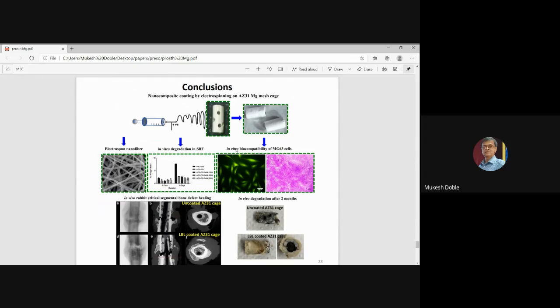Titanium is very widely used because of its strength, because it's easy to fabricate and so on. But the problem with titanium, as I had mentioned, is that it leads to stress shielding. It leads to bacterial adhesion because titanium encourages bacterial adhesion, and it is not biodegradable. So we started looking at magnesium-based alloys. There is some interest nowadays in magnesium-based alloys, with recent papers, as you can see. But the main problem is how to reduce its biodegradation or bioresorption. Also, it produces gases when it is present in the body fluids. How to reduce that? So these are some issues that are being looked at as of now.